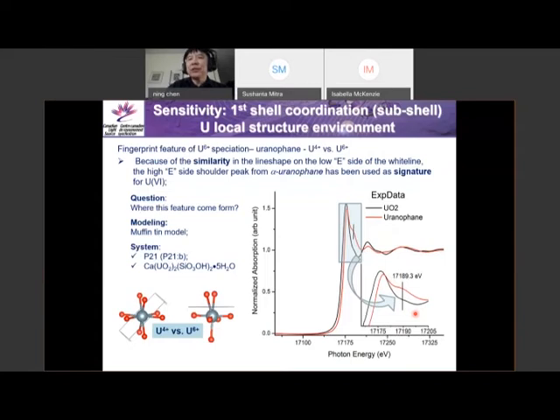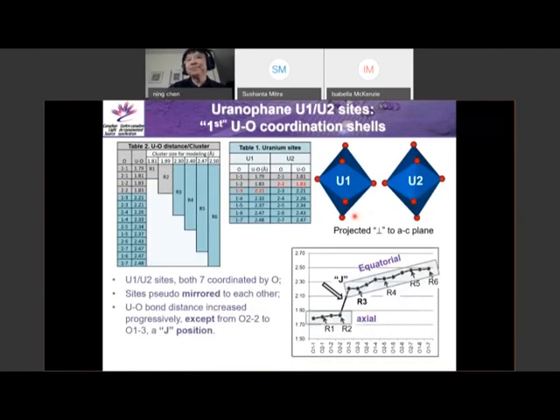When we're talking about the structure components of the system, it can be either bond by bond, shell by shell, and so on and so forth, or side by side. So we have two oxidation states here. And then people said, if you want to identify whether there's a 6+ in this system, you rely on this shoulder peak. Let's see why. This specific system has two per shell. There are two uranium sites here. They are pseudo-symmetric to each other by a pseudo-symmetry plane. Uranium 1 and uranium 2, both of them have an axial here, and then they have an equatorial plane.